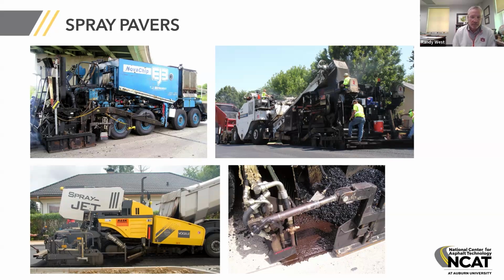It's brown. That means it's not broke. The water is still in the emulsion. But as soon as that hot mix hits that unbroken tack, it will flash the water off, and you'll still be left with the residual binder.